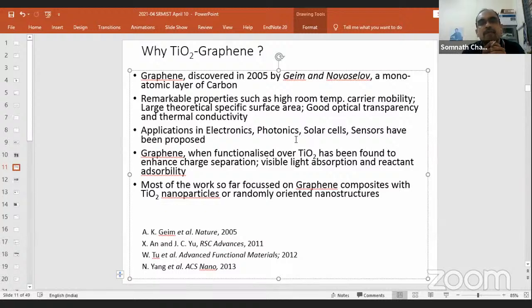So then TiO2 graphene. Why TiO2 graphene has two reasons. One reason is technical, the other reason is personal. Don't think personal means something related to my family. Nothing, but I'm going to explain. The technical reason is that TiO2 is a wide bandgap oxide, 3.2 electron volt, and so it can absorb only UV light. Even if it can absorb all UV light and produce electron hole pairs out of all of it, still it is good. But the point is that it has a lot of recombination. As soon as electron hole pairs are produced, the electrons immediately jump back to the hole and they recombine.